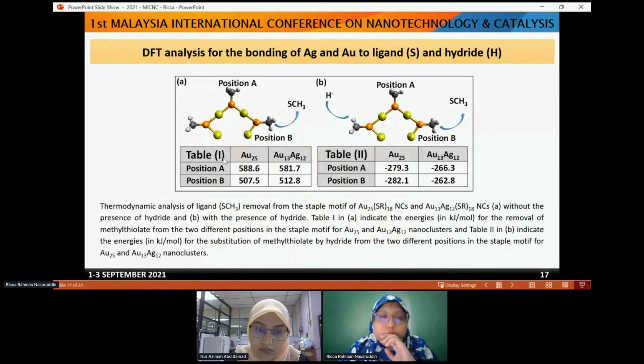If you look here carefully, this is before we add hydride. The removal of the ligand is not that easy. The energy needed to remove the ligand is quite high, about 500. But when we add the silver, the energy is reduced a little bit. Then when we have hydride, as you can see, the energy also decreases. So the presence of silver actually improves the removal of the ligand. And also, as mentioned previously, due to the weak interaction between the silver and the hydride, the catalytic activity can be done faster.